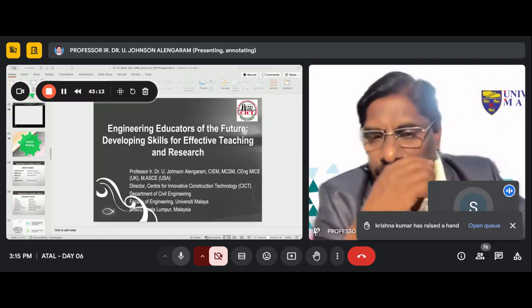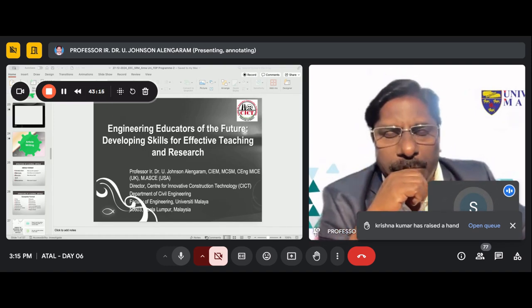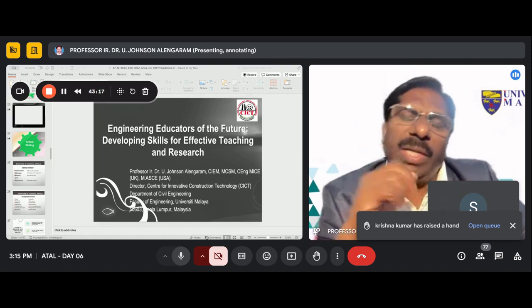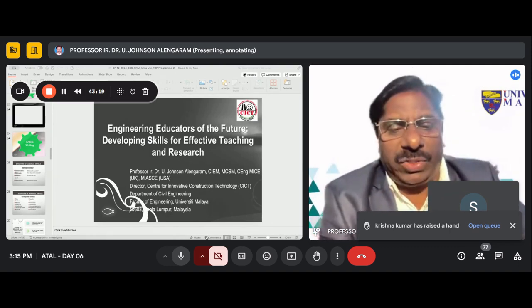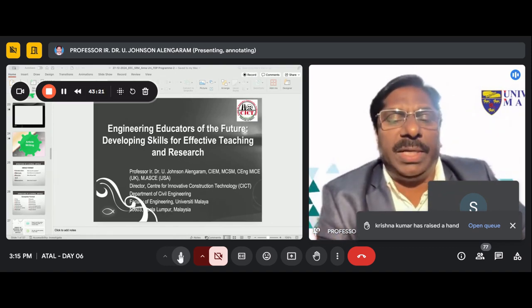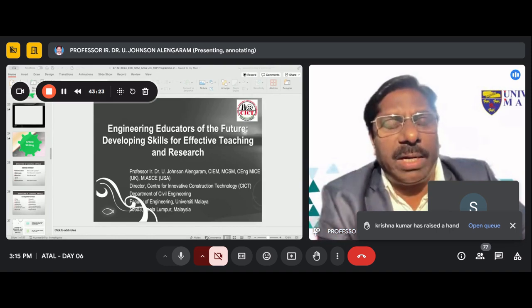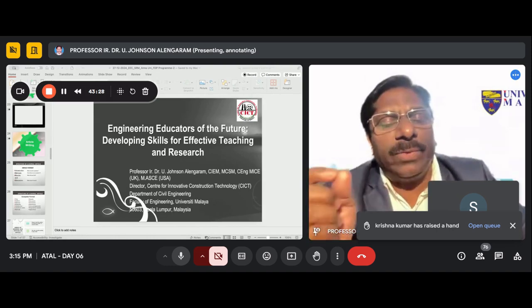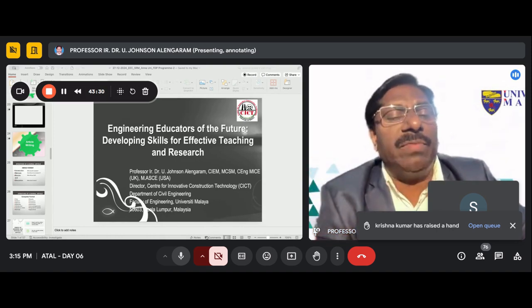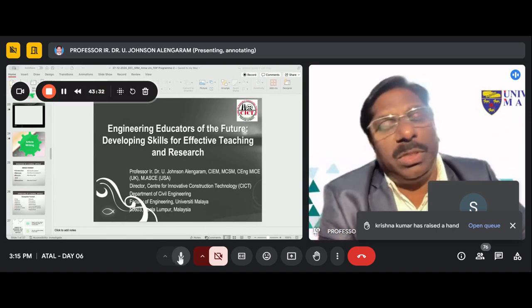You are correct, sir. Is this the general procedure for all organic products? It depends. You have to go case by case, I would say, because this has certain pores inside. We have investigated. The pores are tiny, 18 micrometer, 25 micrometers. So these pores can only be filled with silica fume. You can't use normal cement.